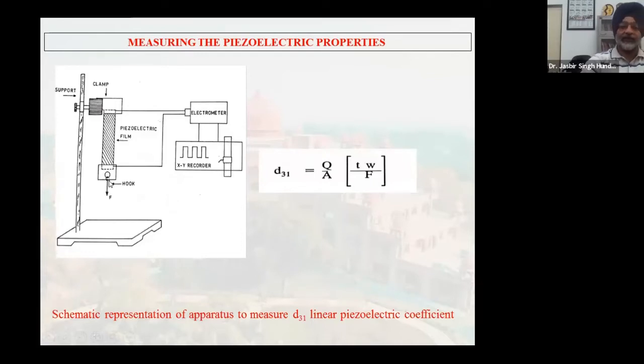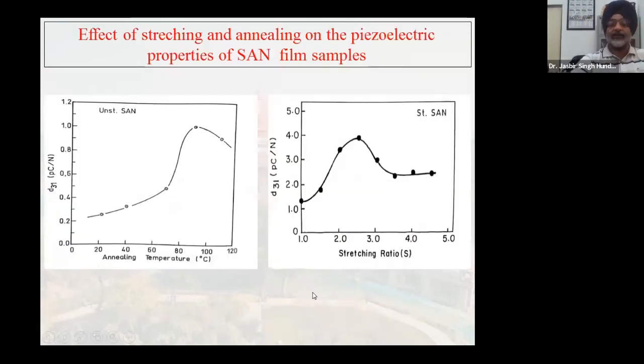We put a small weight in here. We drop the weight along the hook. Then we pick it up. Again we drop the weight, again we pick it up. So we find this kind of recording on the XY recorder. From there, D31 can very well be calculated. So this is also called the linear piezoelectric coefficient, or sometimes the tensile piezoelectric coefficient.